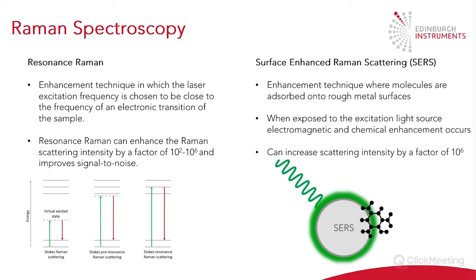Another enhancement technique which is used very frequently is surface-enhanced Raman scattering. This is an enhancement technique where molecules are adsorbed onto a rough metal surface. This rough metal surface also has the advantage of quenching fluorescence, which is great as that's such a common issue with Raman spectroscopy. Enhancements are typically 10⁶, but with the right SERS substrate and sample, you can get enhancements of up to 10¹⁵. With SERS, you can even have single molecules analysed by Raman spectroscopy. The exact mechanisms of the SERS effect are still under debate.